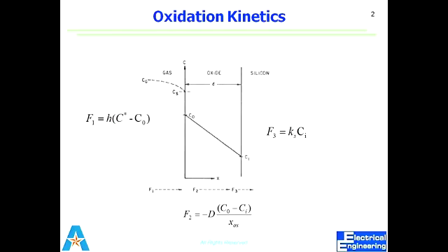On any other substrate, we cannot grow the oxide layer. This is very important. Keep in mind, if you don't have the silicon surface, you cannot grow, but you can deposit, of course. You will have to use some other method to deposit the silicon dioxide layer. But if you say that you can grow, you cannot. And the first experiment that half of you did in the lab yesterday is regarding thermal growth of oxide. You have the silicon wafer, and we put it inside the high temperature furnace. That's why it is thermal growth. At high temperature, the oxygen comes in and reacts with the silicon to grow the silicon dioxide.